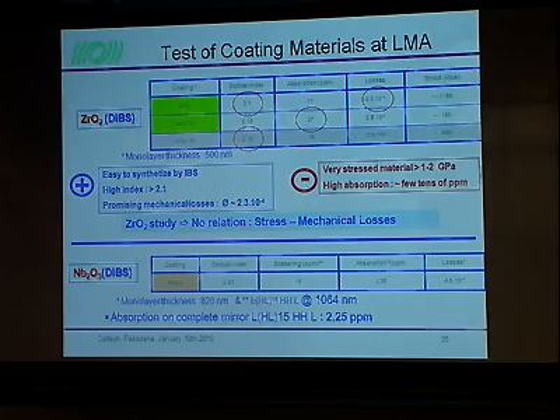Niobium pentoxide has slightly larger losses, because the losses that you see here are at the level of 4.6 10 to the minus 4, so they are at the same level as tantalum pentoxide, but the optical index is larger, so in practice you can deposit thinner films and get the same reflectivity. The absorption was not that bad. We measured a level of about 2.25 ppm, which is a promising number. It's not as good as tantalum pentoxide, but it's something that one can hope to work on and improve. Actually, similar absorption was measured on a full mirror made with niobium pentoxide.